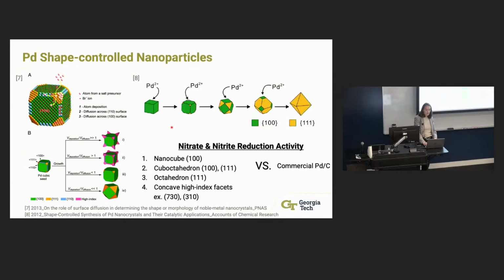And so that's what we were looking at, and if you're familiar with nanocrystal growth, it's really hard and it needs a lot of time. But really, all you need is a seed, and then you need to add ligands or surfactants to basically cap off different ends of the metal to allow for the growth of nanocrystal in the desired direction. And so luckily, there's been a lot of work in this area, and these are papers which demonstrated this first growth in these nanocrystals. And so we were able to luckily draw from literature. Despite there being literature, I do commend Jung Hoon on his work because even a little bit of contaminants in your cell can completely derail the crystallization process here. And so again, we looked at these for catalysts and we compared this to palladium on carbon commercial catalyst.